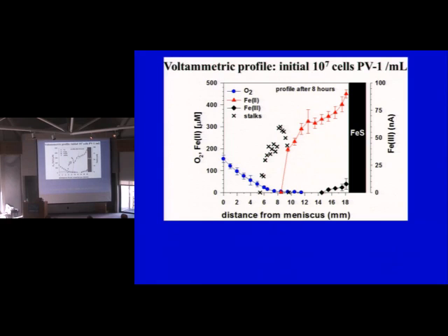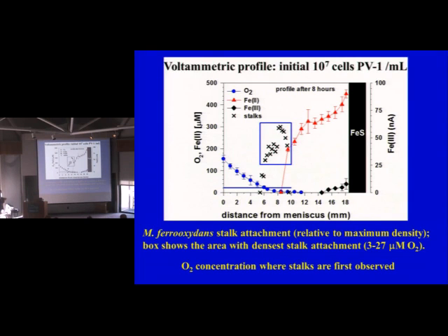Well, why did it crash? Well, it turns out that blue line is about 28 to 30 micromolar of oxygen, and that's where we first see the stalks forming, because this organism forms stalks of iron oxides. That area right there, which has all these X's, that's where we have the most stalks. And it turns out that the oxygen content in that area is from 3 to 27 micromolar oxygen. So these are really efficient forming stalks. You'll see a little bit of abiotic precipitate, but most of this is stalks. So we actually are showing that at this point, we're at about 3 micromolar, and at that point, we're about 27 micromolar. That's pretty interesting.